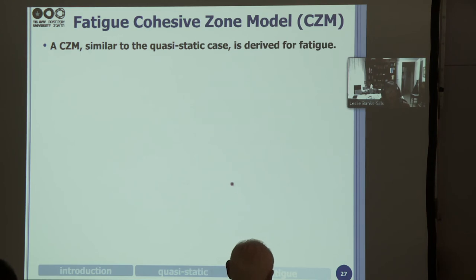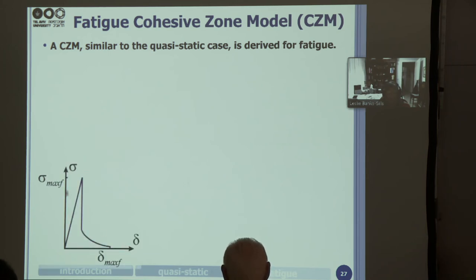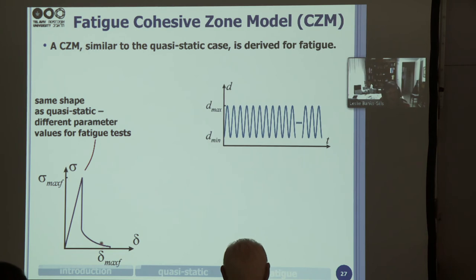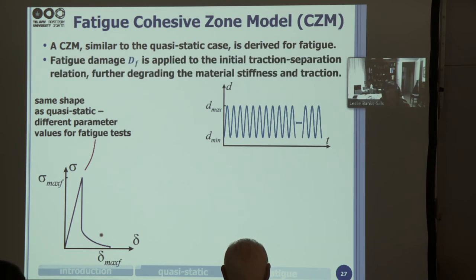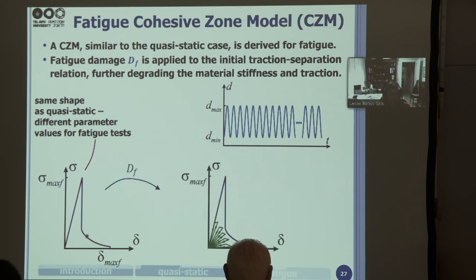So the CZM that we created is similar to that of the quasi-static one. Here is the basic traction separation law, where we now write sigma max F and delta max F. And it has the same shape as the quasi-static one, but we have fatigue damage. And we apply fatigue damage to the traction separation law, further degrading it. We have the quasi-static damage, which is in the softening part, but we even have fatigue damage, which decreases this curve. And this is just shown schematically that as we fatigue, the curve is decreasing.